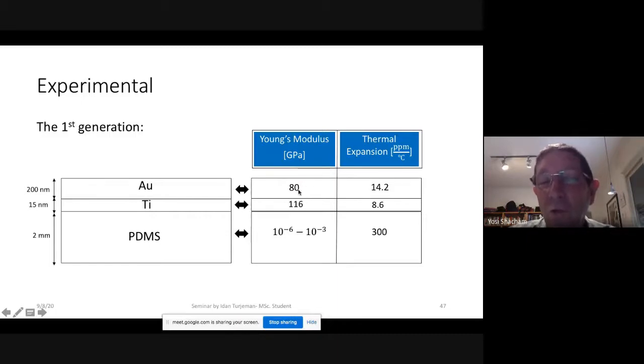I'm showing you this to show a very important issue. The materials have their hardness. The Young's modulus of gold is 80 GPa, and thermal expansion is 14.2 ppm per degree Celsius. The PDMS is 10 to the minus 6, 10 to the minus 3. You see a huge mismatch in the Young's modulus, in the mechanical properties. And you can say, this is a very soft material, who cares, nothing will happen. This is gold, gold is strong, gold is hard.